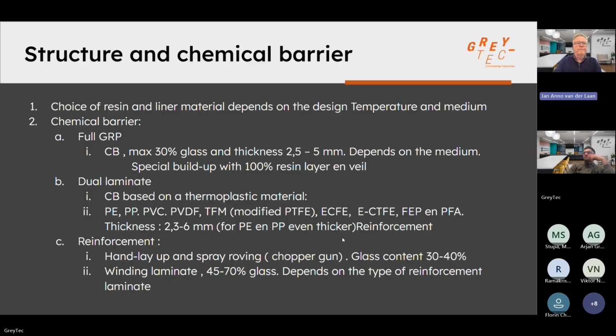The structure and the reinforcement. The chemical barrier of a full GRP product typically has a thickness of, let's say, 2.5 to 5 millimeters and consists of resin and glass. In dual laminate constructions, the chemical barrier is made from a thermoplastic material. The reinforcement structure provides the mechanical strength and can be built up using different laminate configurations depending on the application.